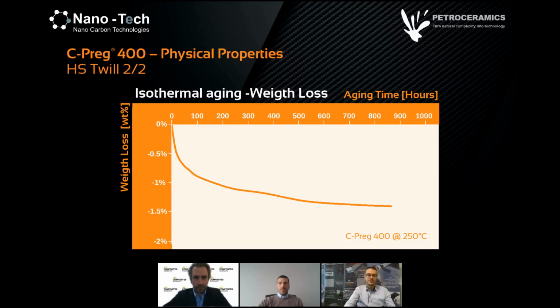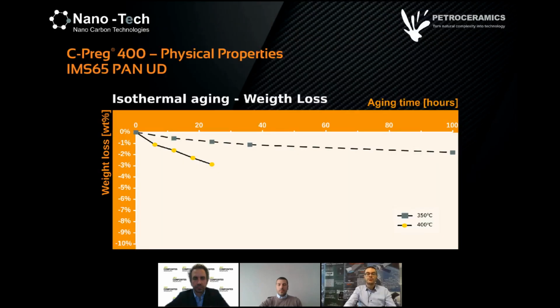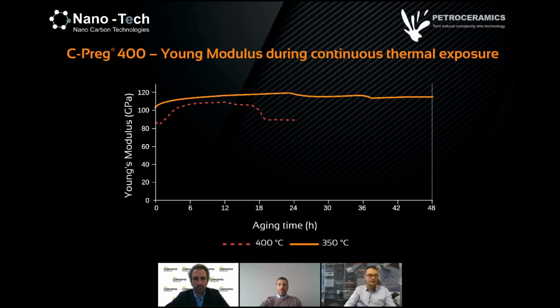And also, we performed some isothermal aging to check the weight loss over prolonged exposures at 250 degrees up to 900 hours. And you can see we have very negligible weight losses because they are less than 1.5%, and most of it is at the very beginning of the tests, and it is ascribable mostly to sizing of fibers and to the completion of the curing of the composite. We also performed isothermal aging to check the weight losses at higher temperatures. So we tested for 100 hours of exposure at 350 degrees, and you see the little weight losses. And also we tested for 24 hours at 400 Celsius degrees. So basically, we can say that we have good thermal stability over temperature and over time, and good thermal stability